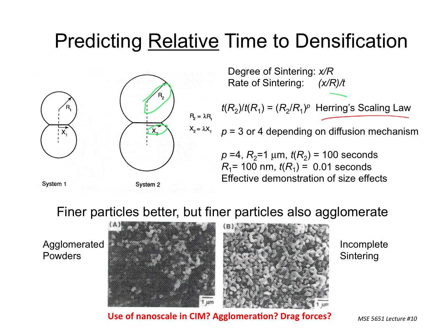But anyway, Herring's scaling law says that the rate of sintering for two different particle sizes is equal to the ratio of R2 to R1 to some power P, 3 or 4 depending on the diffusion mechanism. If R2 is 1 micron, the time of sintering is 100 seconds, whereas if R1 is 100 nanometers, the time of sintering is only 0.01 seconds. So this law becomes useful in providing some simulation of the time involved when these diffusional processes are happening.